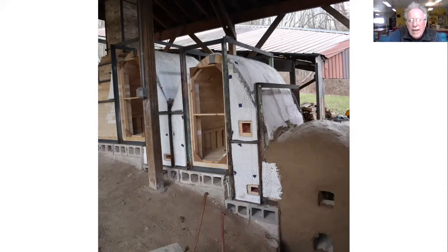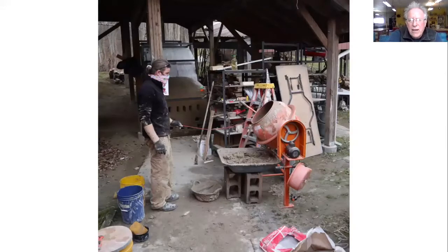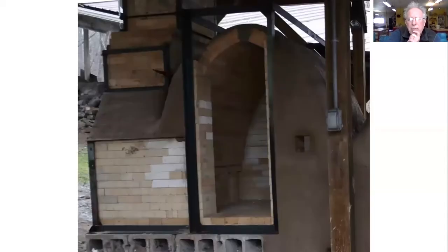So it's covered with a castable, and that castable is mixed just like cement would be mixed in order to do a concrete foundation. The castable is a mixture of Portland cement, and sand and fire clay and sawdust. Kristen mentioned our local cement dealer who made a very nice donation. So those are the main ingredients of the castable. It's put on by hand and then troweled.